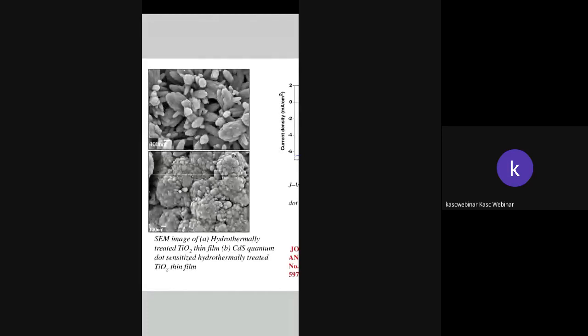And moving on to another type of modification, surface modification. Another type of surface modification is done by the hydrothermal method. Here the two SEM images show titanium dioxide. The first SEM image, A, shows hydrothermally treated TiO2 thin films, and B shows quantum dot sensitized TiO2, the same hydrothermally treated TiO2 thin films.